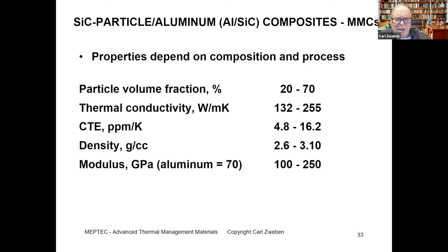You notice the density is in the range of aluminum. As the particle volume fraction goes up, the density goes up, but it's still no more than about 10% higher than that of aluminum. The modulus also increases. Aluminum has a modulus of 70 gigapascals, and so we get higher moduli with these composites than we do with aluminum. And this is so far the most successful commercial advanced thermal management material. However, the thermal conductivities are still in the range of aluminum and we would like higher values.